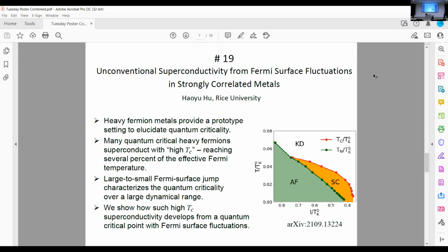In addition, in various materials, there is a large-to-small Fermi surface jump at the antiferromagnetic quantum transition point. Here we study this model from a theoretical perspective, to address how such high Tc superconductivity can develop from this Fermi surface jump, or in other words, from the large-to-small Fermi surface fluctuations. Here is our theoretical phase diagram, where we can see a broad superconductivity region appears near this quantum critical point. More details are in the poster.